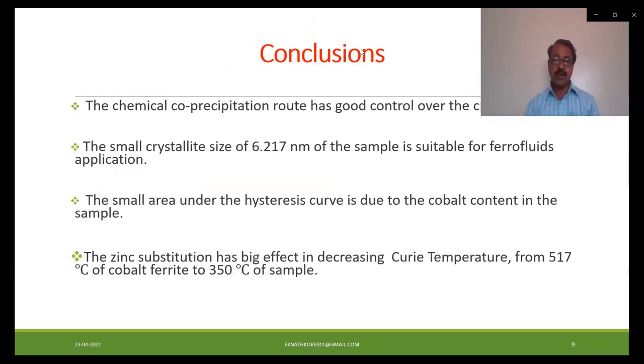I conclude with these points. The chemical co-precipitation route has good control over the crystallite size. The small crystallite size of 6.217 nanometer of the sample is suitable for ferrofluid application. The zinc substitution has a big effect in decreasing Curie temperature from 517 degrees Celsius of cobalt ferrite to 350 degrees Celsius of the sample.